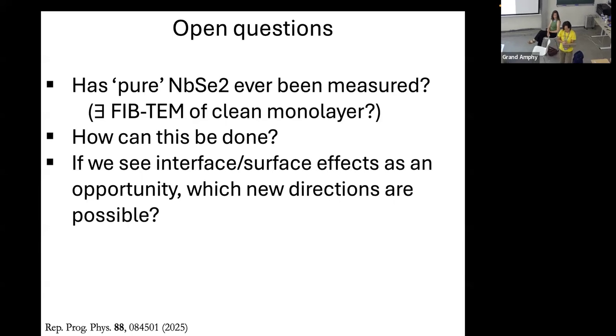Does the TC depend on the substrate, using epitaxial layers? Yes. Probably yes. But I'm just saying that. I agree that this, at least in tunneling, your community does that, and the question here is whether the same trend in TC versus thickness exists there. For example, people measure the 2 layer, 3 layer, 4 layer.